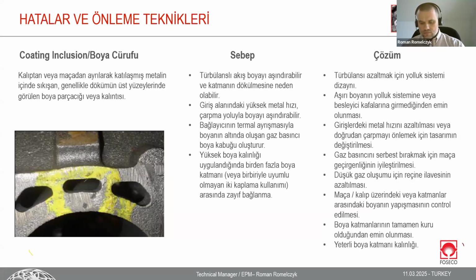So to prevent it, of course, it's opposite what I say. We can calculate once again the runner system. So redesign, use a different way of application of the coating to be sure that it's adhesive and sticking. It's enough to take care about the running gate itself, that it also should be covered by the coating. So many possible solutions.